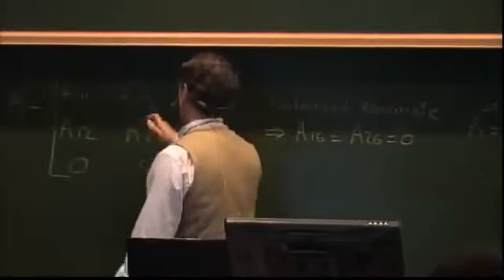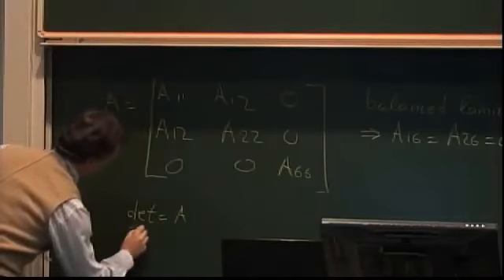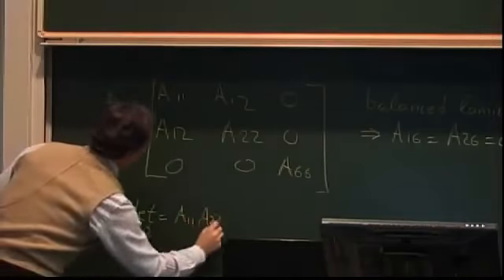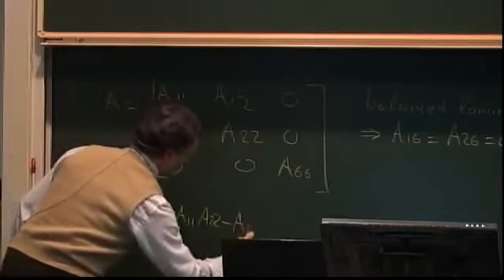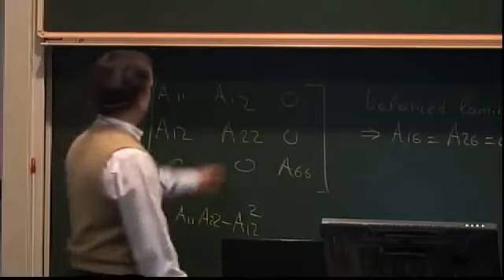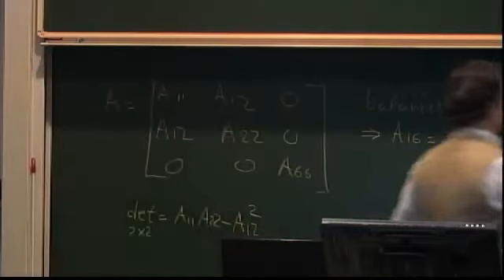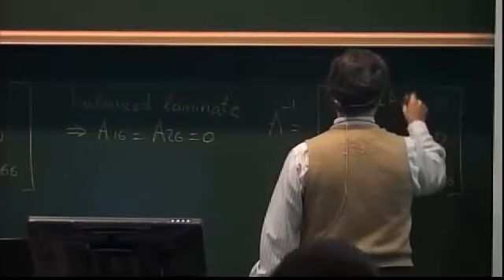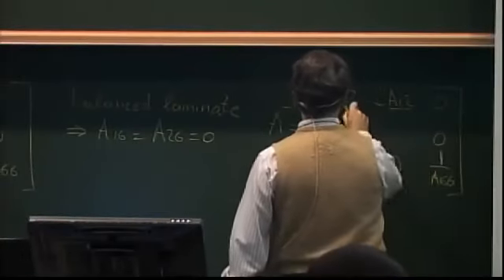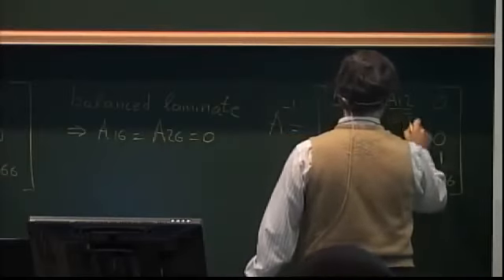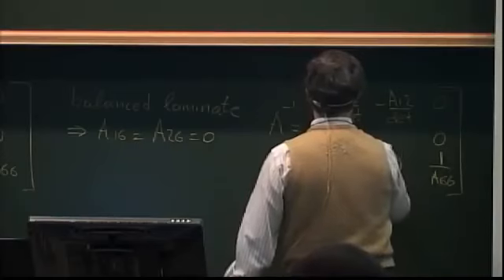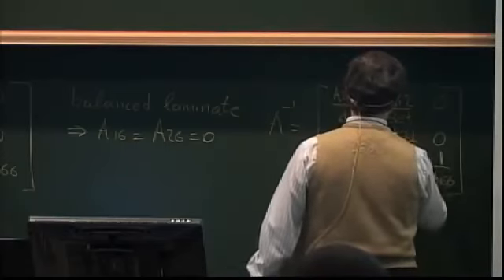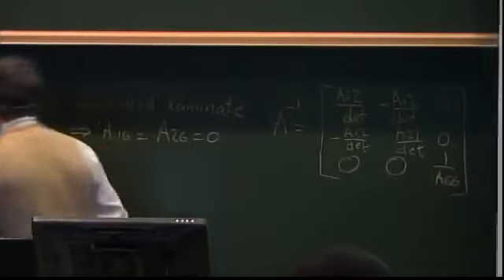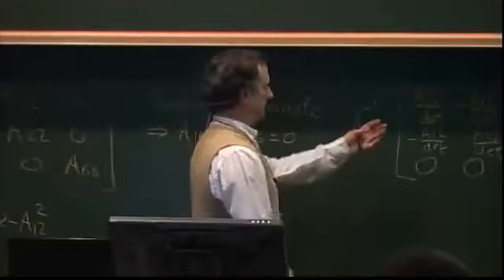And to invert this guy, I need to calculate the determinant, which is the determinant of the 2 by 2 only, A11, A22 minus A12 squared. And then I take this term and put it there. So it's A22 over the determinant, then minus A12 divided by determinant. Let's not call it delta because it gets confused with the discriminant. And then it's symmetric, minus A12 over the determinant and A11 over the determinant. Now I know that these days you just ask Maple to do it for you, but to at least convince you that this might be the correct one.